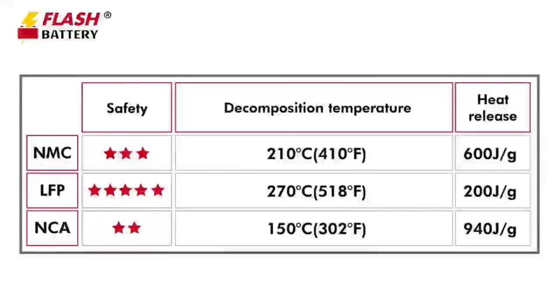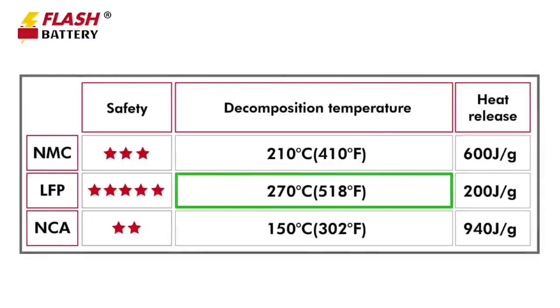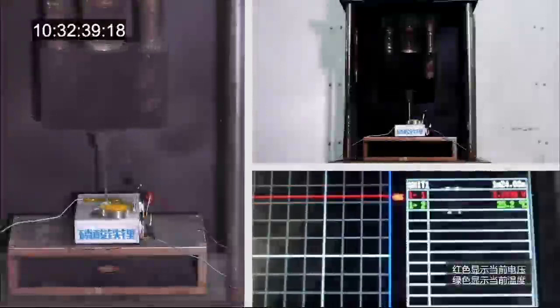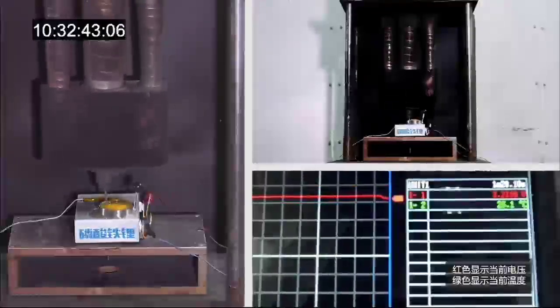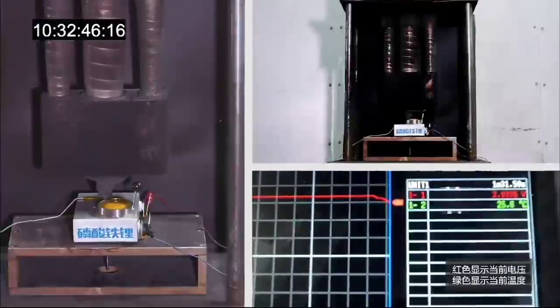LFP, on the other hand, starts decomposing and releasing oxygen gas at 270 Celsius. When it decomposes, it only releases 200 joules per gram. This means thermal runaway is triggered at higher temperatures, it's less violent, and less oxygen is released.